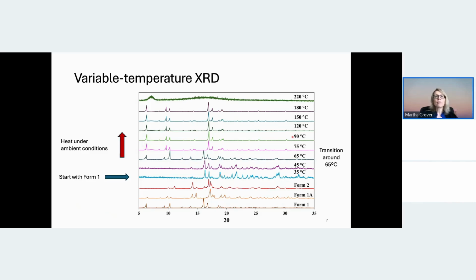And finally, we performed variable temperature XRD. This is an ambient condition, so it's not dry like we had for the DSC and TGA. We started here with our Form 1 and then heated in the XRD. We have these peaks that look very similar to the Form 1 peaks until we get to 65. At 65, we're starting to see some transition, especially in this region over here.